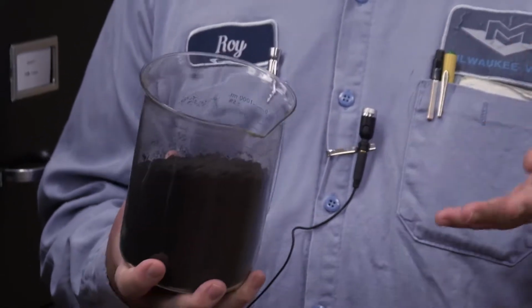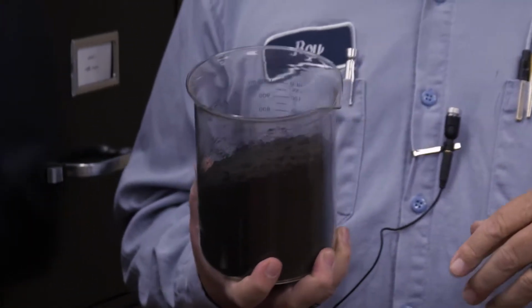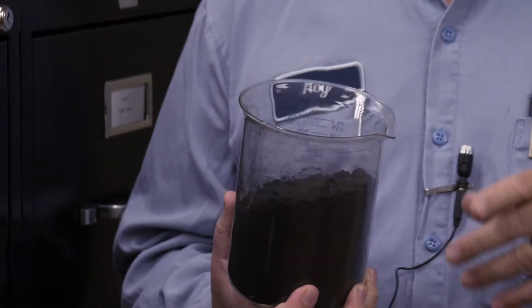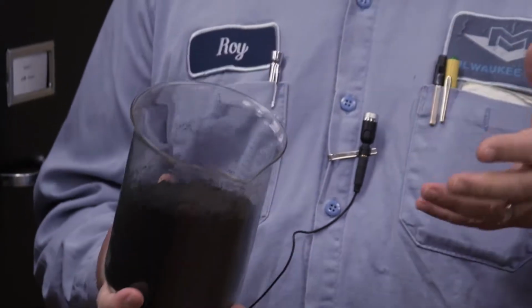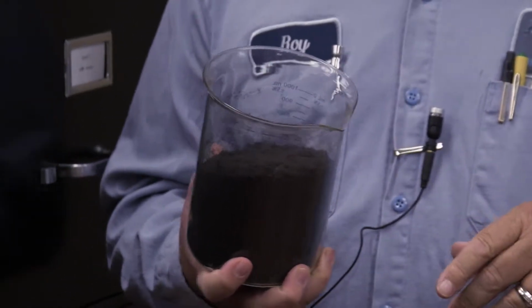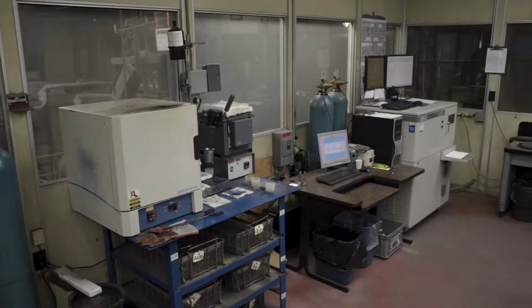We do sand testing every batch of sand. We test the sand in the return sand bin. We test it for moisture and temperature, and then we drop that sand into the mixer. The mixer will mix the sand, and it'll add the 4,500 pounds of sand with the clay and new sand replacement. It'll drop into the mixer, we'll mix it, add water to get to our set point, and then when it's discharged into a return sand bin, as it's discharged, it's checking the sand to see what the compactability and moisture and clay content is of that sand electronically.